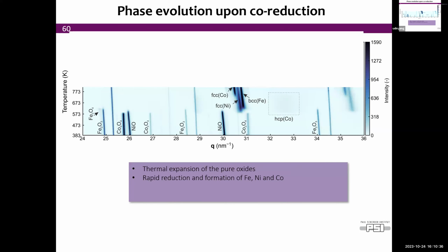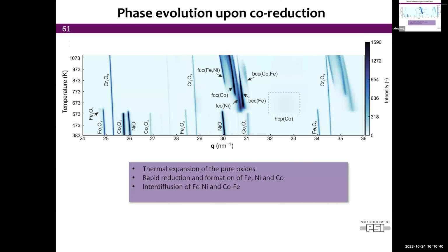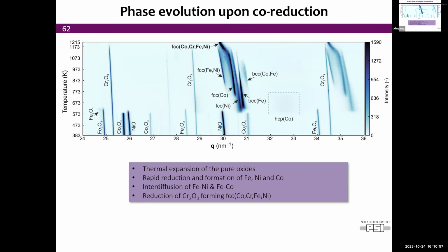And the next step is interdiffusion of iron with nickel and cobalt with iron. So we see now this FCC iron nickel intermediate alloy, as well as a BCC cobalt iron. So they are, of course, different crystal structures. So we end up with different diffraction peaks. And then finally, you see that the chromium oxide had done nothing. It was simply sitting there, because after all, it's supposed to be stable.